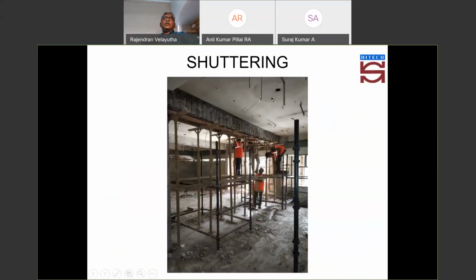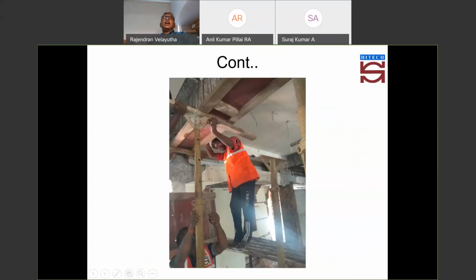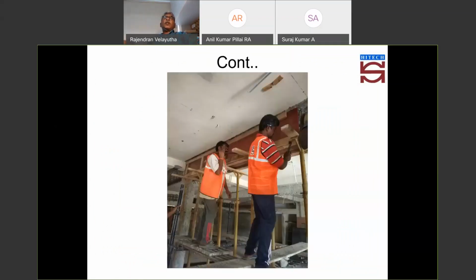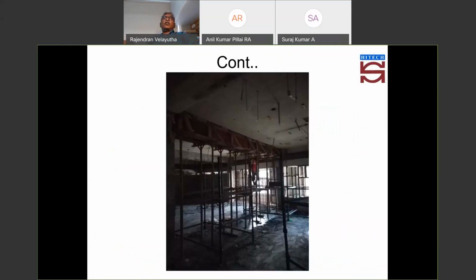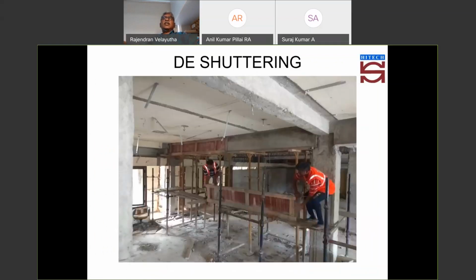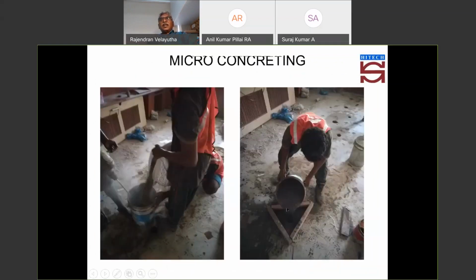and on the top, cores have been made for pouring this microconcrete. The beam bottom has been put and sides also placed, and once the beam bottom and sides are placed, from the top you have to pour this microconcrete mix and then pour continuously. What is more important is you have to maintain the hydrostatic head. For maintaining the hydrostatic head, you need to have some system like this. 100 mm thick runners have been provided like this.